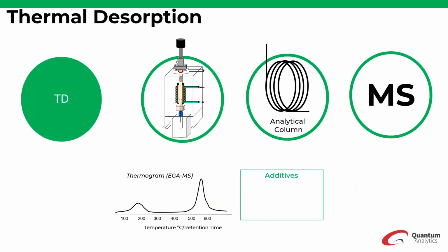For example, in thermal desorption, we switch to an analytical column this time. The sample cup is dropped, the temperature is ramped, just like in EGA, but we now have separation of all of the pyrolysates that you thermally sampled, and you get a nice chromatogram at the end. This is really ideal for things like additives or any lower molecular weight compounds that you may want to thermally desorb out of your sample.